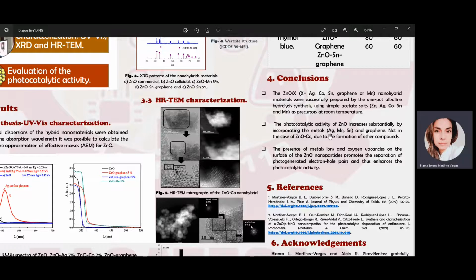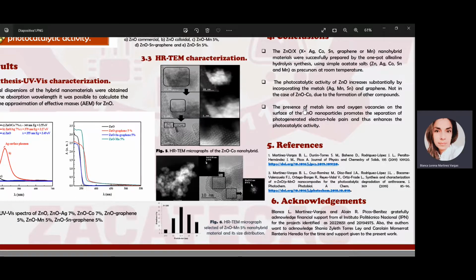Also, the photocatalytic activity of zinc oxide increases substantially by incorporating the metals, especially silver, manganese, and tin, as well as graphene. Not in the case of zinc oxide with cobalt, due to the formation of other compounds. The presence of metal ions and oxygen vacancies on the surface of the zinc oxide nanoparticles promotes the separation of photogenerated electron-hole pairs and thus enhances the photocatalytic activity. The references on which this work is based can be seen here.